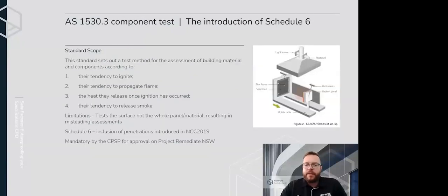AS1530 Part 3 component test and the introduction of Schedule 6. AS1530 Part 3 is for material fire hazard properties and is the second test, which involves a sample being progressively moved closer to a radiant heat panel. The test goes for 20 minutes, and over that period it tests for ignitability, flame spread, heat release, and smoke release. One flaw with this test originally was that it was used to demonstrate compliance for polyethylene composite panels. Because there were no penetrations through this, it only tested the aluminium, which gave it great results. This has been changed with Schedule 6 of this test, which mandates that penetrations must be done with this test so it can give an accurate representation of all layers.